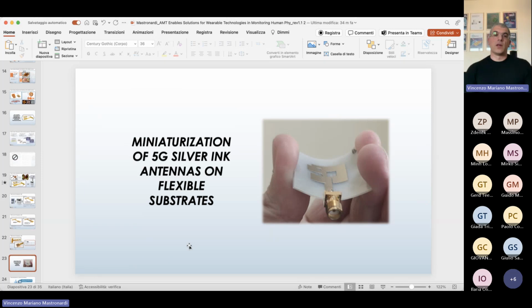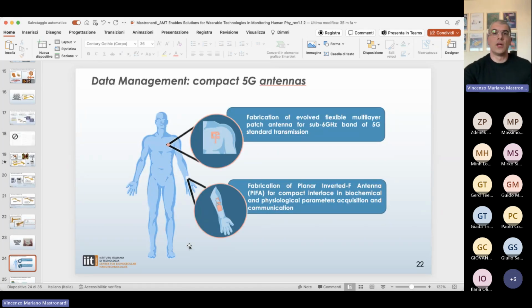But we also exploit the Dragonfly 4 from Nano Dimension to develop and build miniaturized 5G antennas made of just conductive silver ink, directly printed on alternative substrates such as polyethylene naphthalate. The idea is to develop compact 5G antennas that can be used as a compact interface in biochemical and physiological parameter acquisition and communication with the external circuitry. For that reason, we developed two different kinds of antennas.